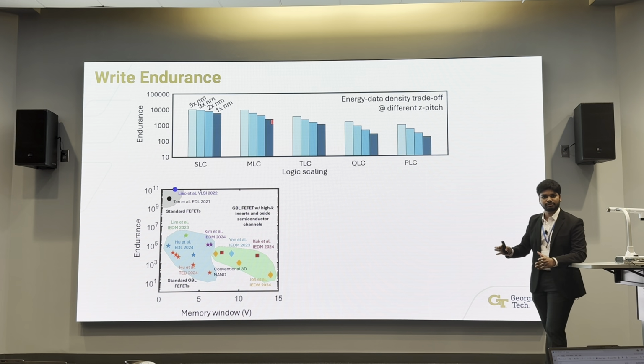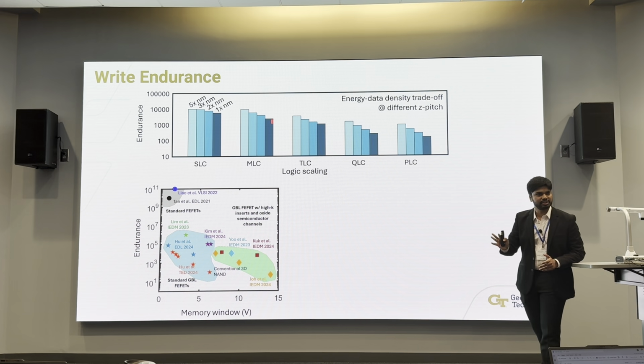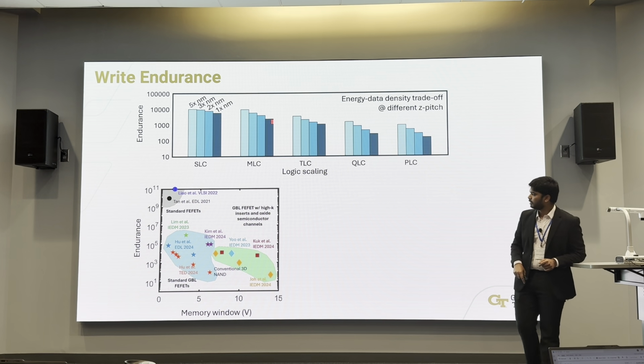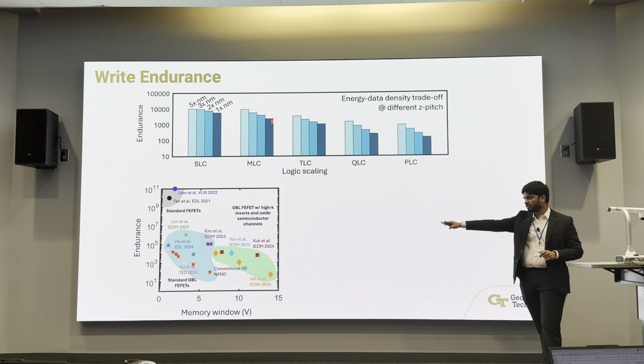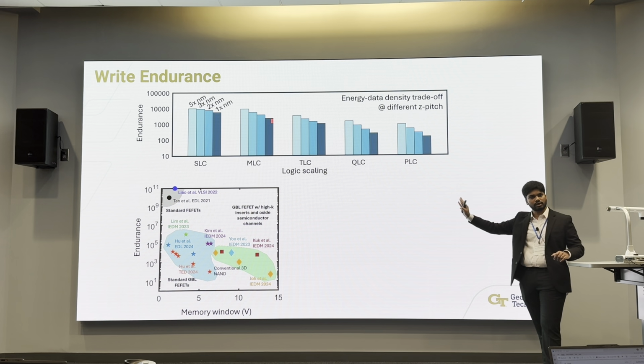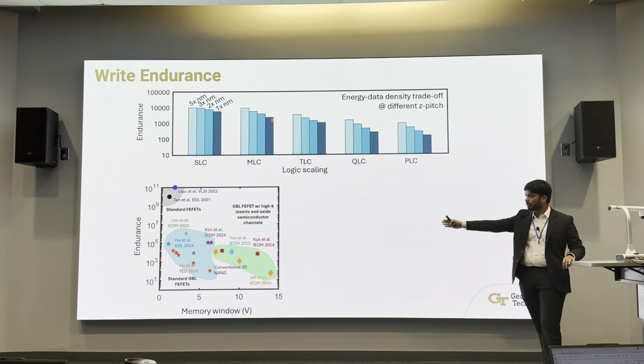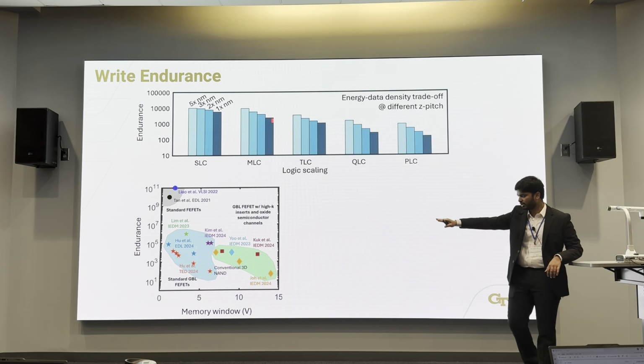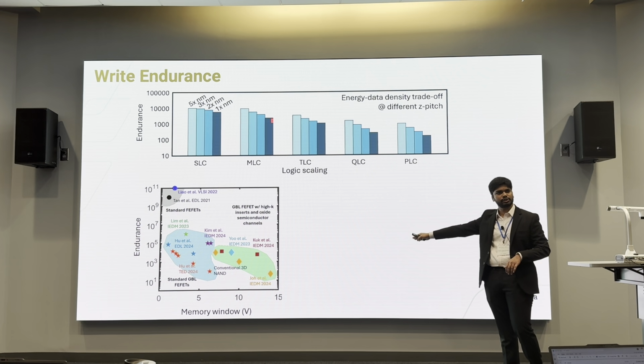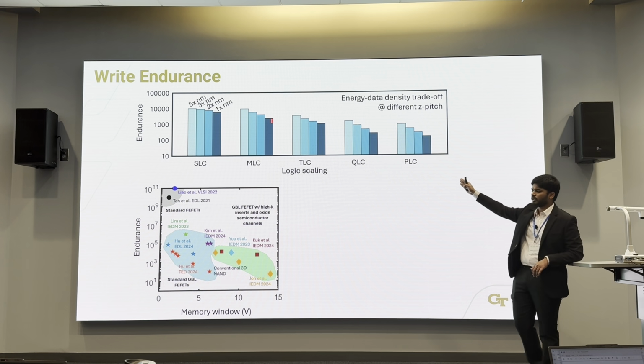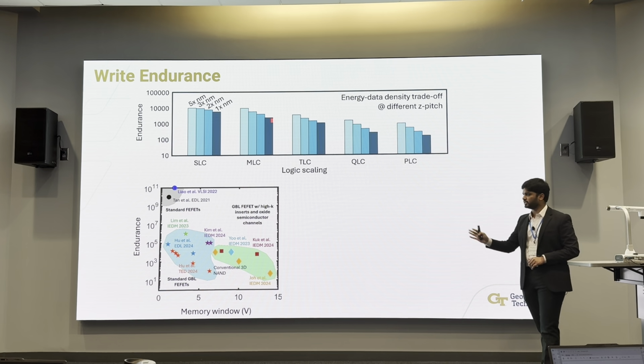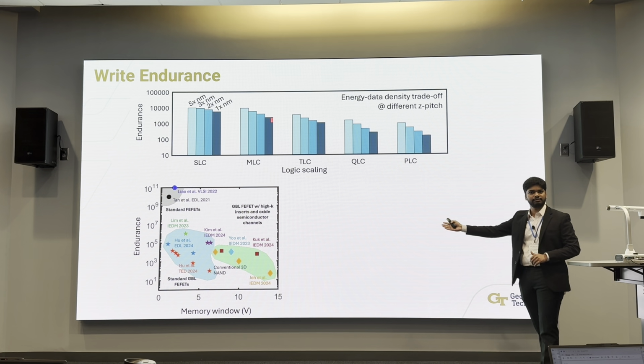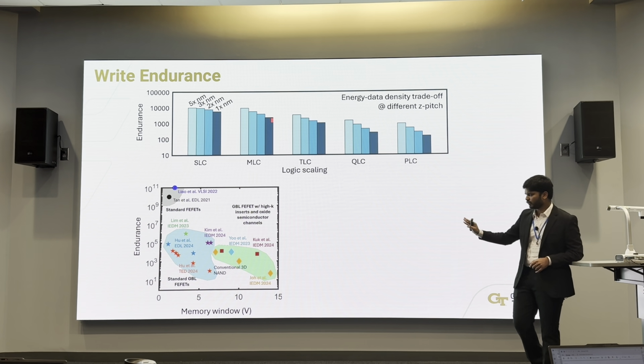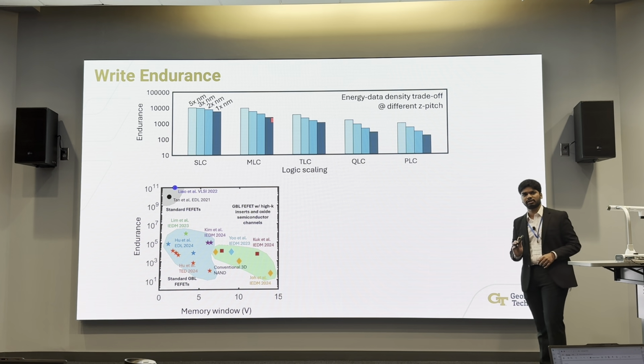Commercial NAND that is being shipped out now, which is QLC NAND, has endurance of the order of higher hundreds to the lower thousands. So if you can see at the bottom there is a benchmark showing all the large memory window FeFETs. And we see that as the memory windows increase, the endurance continues to drop, pretty much similar to how it happens in the case of CTF, which means we should be able to throw this into CTF and make products out of it. But unfortunately, that is not the case. Ferroelectrics have a different problem.